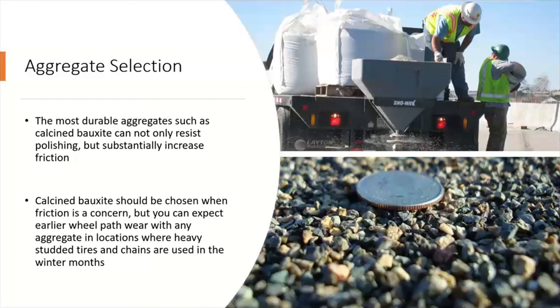Some of the aggregates, like especially some of the things like flint, were prone, even though they were really good, durable, highly polish resistant aggregates, when it came to heavy traffic over a number of years, they would polish. And with heavy traffic and ice and things in the winter, they were seeing a few crashes as it related to friction numbers. And that was mostly in the wheel path. So they started the trend with using calcined bauxite, which is incredibly polish resistant.